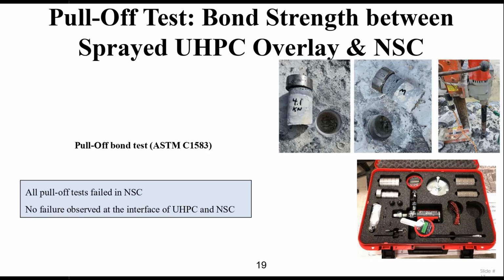Okay. Is water vapor trapped underneath the layer of sprayable UHPC? Yeah, I'm not sure what they mean by that, but if you wet the surface, I mean, the surface is wet, you spray the UHPC. I think that's what they're trying to say. No, there is nothing trapped between the two layers, the normal strength concrete and the sprayable UHPC. There is nothing trapped in there.